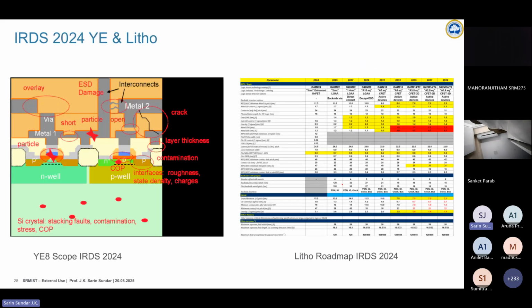And yes, this is about the IRDS. You will also find a classification of defects in IRDS and where they come from. Right from the material in the crystal: stacking faults, contamination, stress, and also how the silicon wafer is prepared. That's why we never use a silicon wafer as it is in the factories. You have to grow an epitaxial, highly pure silicon layer first, and only then start your device fabrication on top. And between the devices, you have overlay errors. Between the interconnects, you have ESD damage, sometimes cracks, and also layer thickness, uniformity, and contamination, and as you have seen earlier, different processes can contribute. You will also find many of these things listed in the litho roadmap document, again in IRDS.